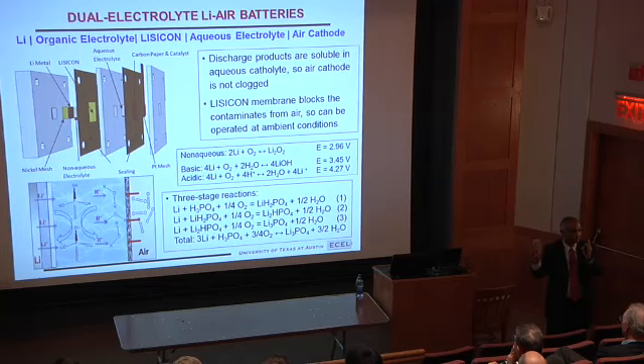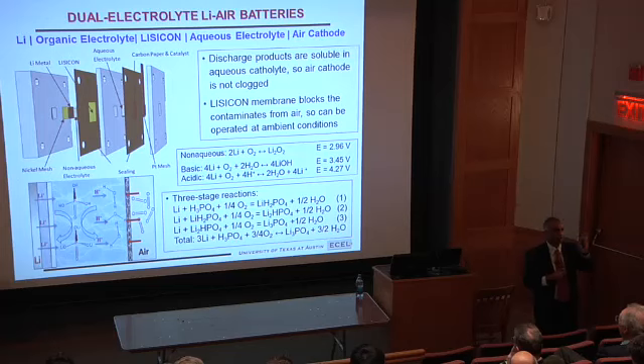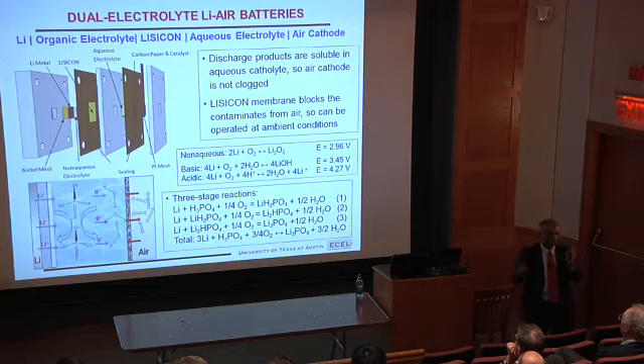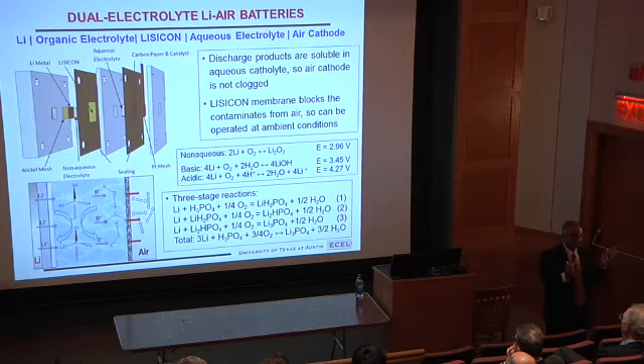And the catalyst I'm talking about should reduce only the oxygen and then oxidize the oxide ion. And when you have an organic electrolyte, that catalyst will degrade the electrolyte first before it does anything with the oxygen or oxide ion. Challenge. And then you form lithium peroxide, in a non-aqueous electrolyte, not soluble. It goes and clogs all the air electrode pores, so oxygen cannot get in. What a mess. And it is very hard to solve all those problems.